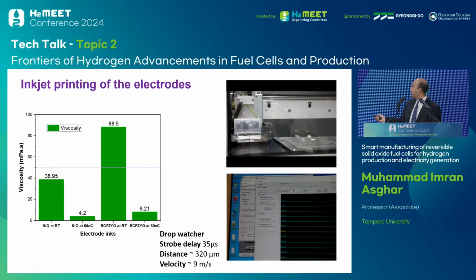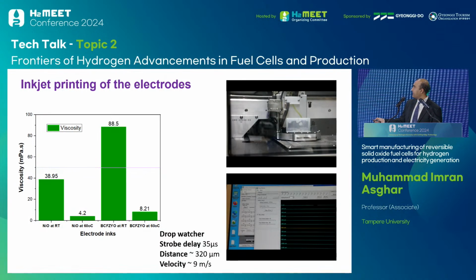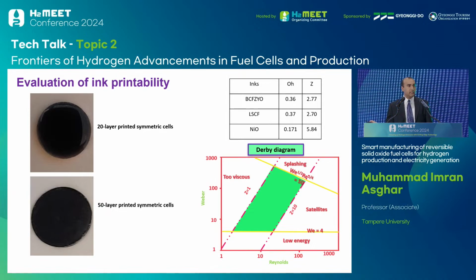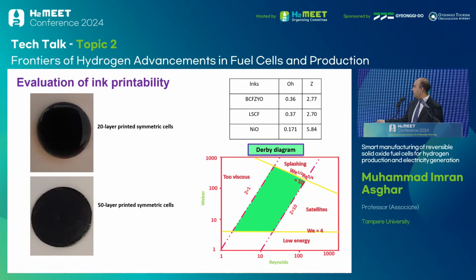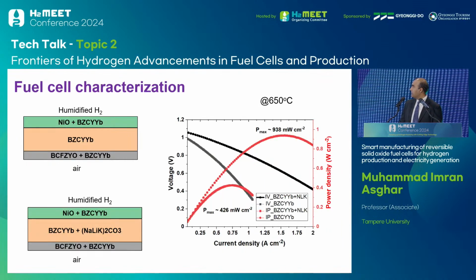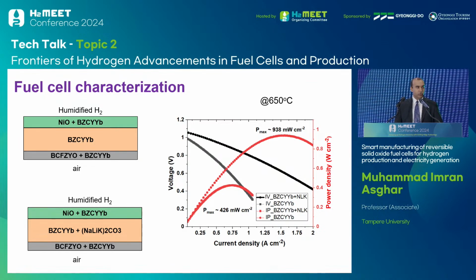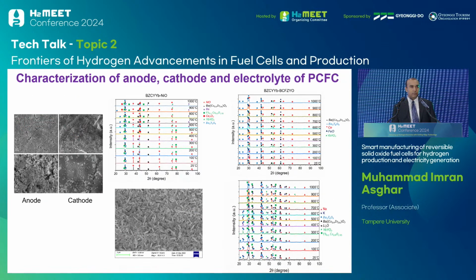So here you see the inkjet printing of our electrodes. And here you see the Z number for our inks. They all fall in the green region in here, so they all have good ink printability. There we see 20 printed layers, and there we have 50 layers. So this is how the cell looks like after printing. When we measured these cells electrochemically, we found performances of about 938 milliwatts per square centimeter in different configurations. These cells are stable, so we have tested them in different long-term stability tests. These cells have demonstrated long-term stability.